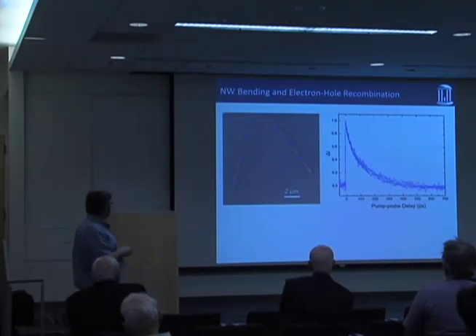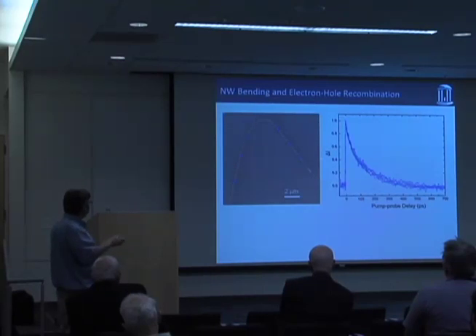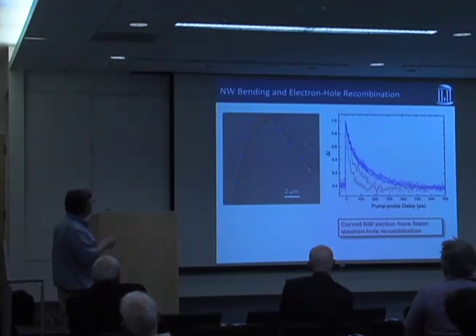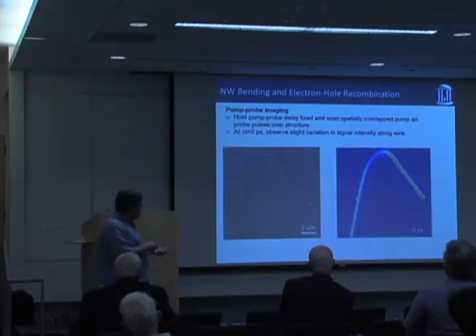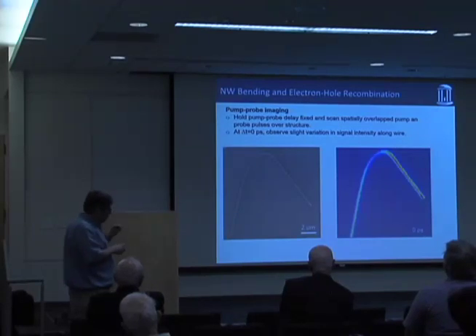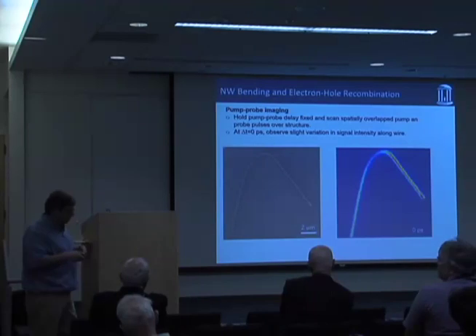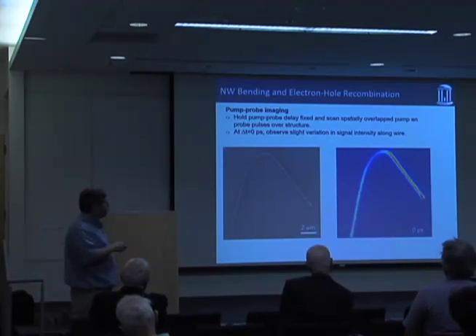And so we started looking at these bent wires. So here's a bent wire, and if you measure the kinetics at all these different points, you get these blue curves. There's actually 3 transients there. They all overlay. But you look in the bent segments, and they're faster. And in fact, you can do the transient absorption imaging in a slightly different mode. So in this one the pump and the probe are spatially overlapped with each other, but I'm going to drag them across the structure at a fixed time delay and get an image of what the transient absorption signal looks like across the structure. So at 0 picoseconds, it looks something like this. You might have hoped that it would be uniform across the structure. It turns out that it's not, but we understand why it's not.